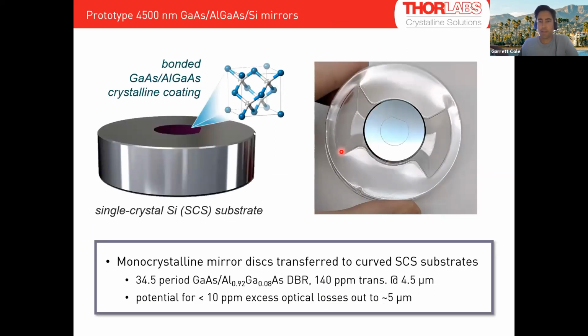This is the same GaAs/AlGaAs multi-layer material, but we transfer to a different substrate. Obviously, glass isn't going to work anymore out here. So we use things like single crystal silicon, more recently some work on calcium fluoride, and there can be others. Basically, we just tailor the design of that Bragg mirror to work at these longer wavelengths, so obviously a thicker quarter wave condition and so on.